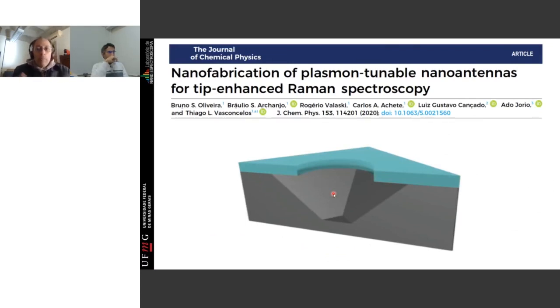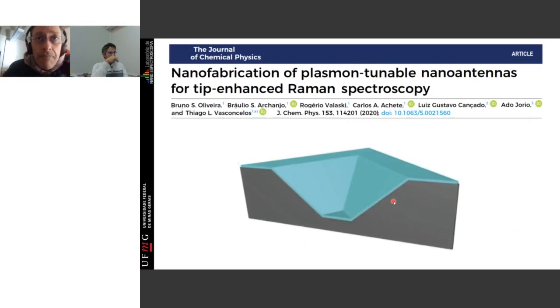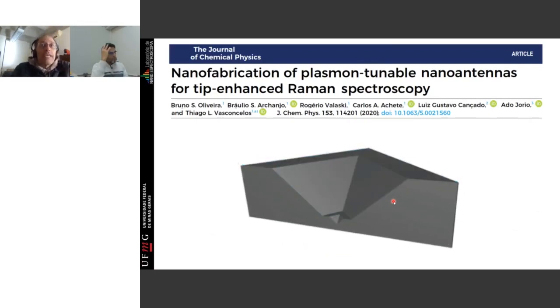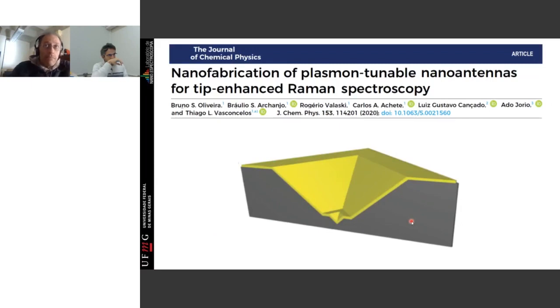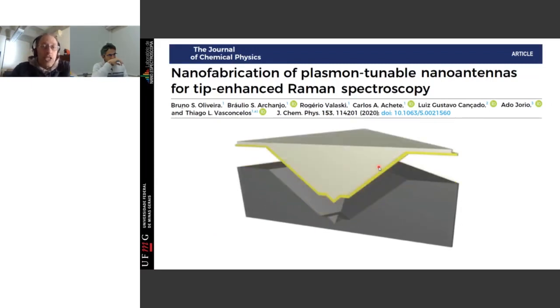And this hole will respect the silicon crystallographic orientations, and this will actually become like a pyramid. And then you oxidize the silicon again, and you open a hole again, and then you do the process of corrosion again. And then you have the shape of our nano antenna. Here you evaporate gold, and then you come with a glue, and you detach the gold, okay?